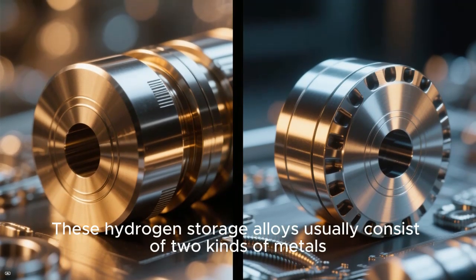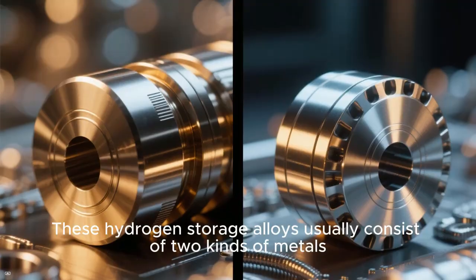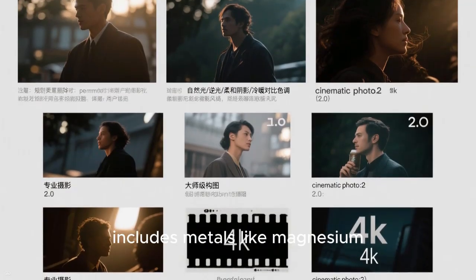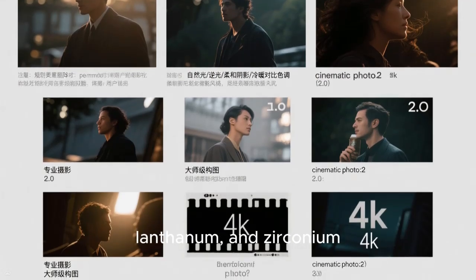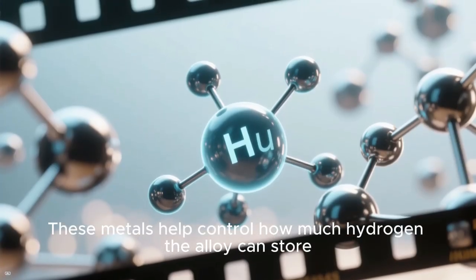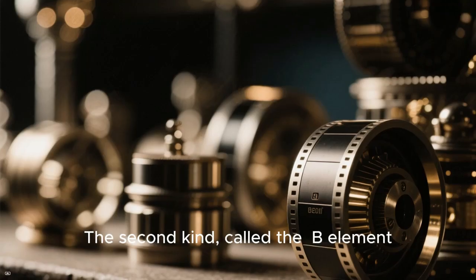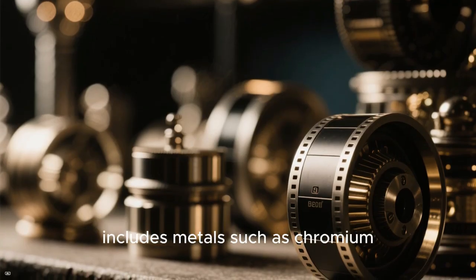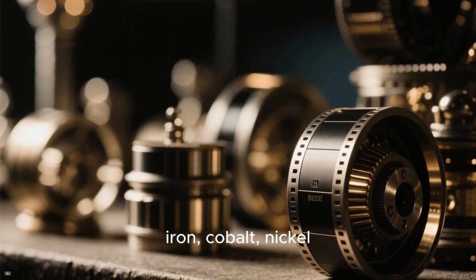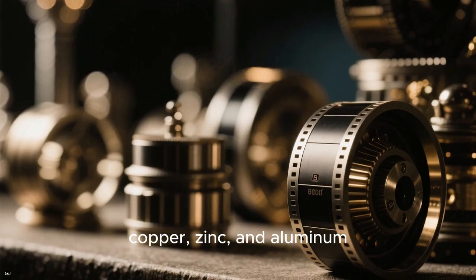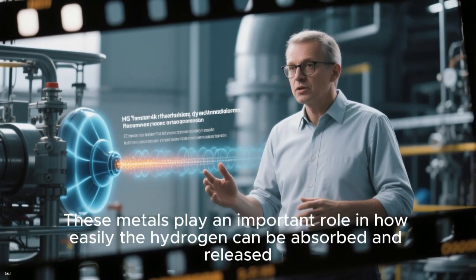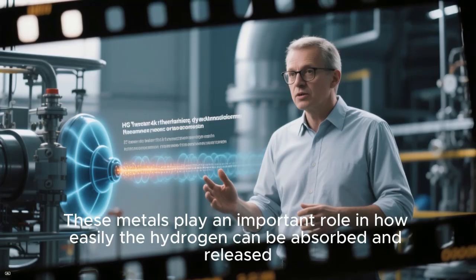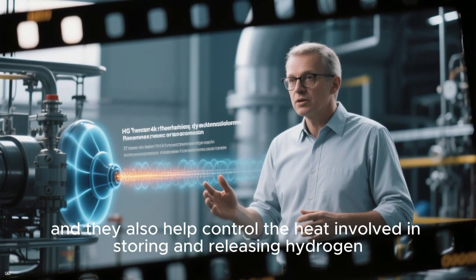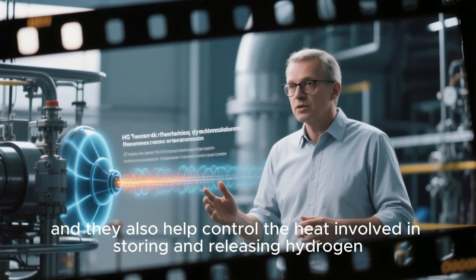These hydrogen storage alloys usually consist of 2 kinds of metals. The first kind, called the A element, includes metals like magnesium, titanium, vanadium, lanthanum, and zirconium. These metals help control how much hydrogen the alloy can store because they have a strong attraction to hydrogen. The second kind, called the B element, includes metals such as chromium, manganese, iron, cobalt, nickel, copper, zinc, and aluminum. These metals play an important role in how easily the hydrogen can be absorbed and released, and they also help control the heat involved in storing and releasing hydrogen.